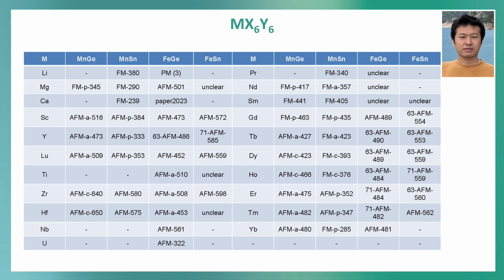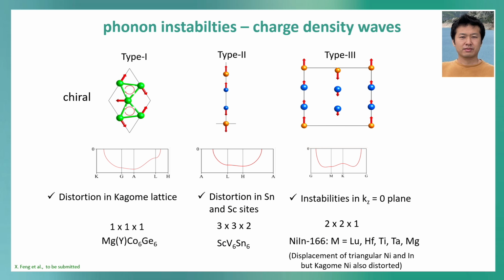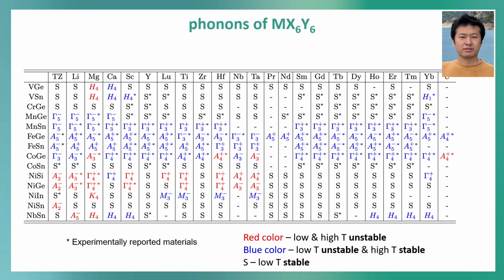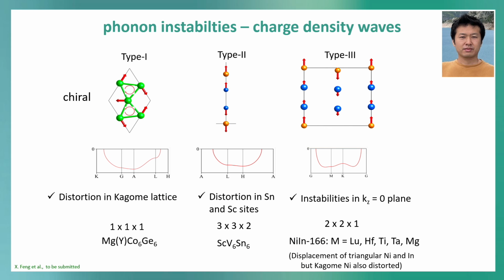So now we did it for all these A elements, and manganese germanium 166, manganese tin, and so on. There are a few compounds known as antiferromagnets. There are a few compounds not known. There are a few compounds having a structural distortion. And indeed, we could identify 3 types of charge density wave instabilities in the Kagome lattice. So it shows already that in this 166 compound, which has 1,000 members, we can have different instabilities. Now I'm too fast again. Takes some time. Okay, so different instabilities.